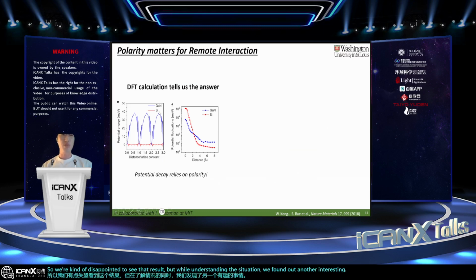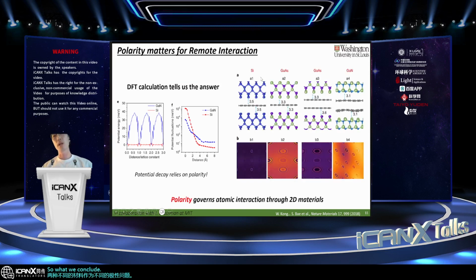We did a DFT calculation, and what we found is that the compound semiconductor can produce very strong potential fluctuation even through the monolayer van der Waals material, while this elemental semiconductor cannot do that. So these two different materials have different polarity properties. What we conclude is that polarity matters for the potential fluctuation through that van der Waals material.